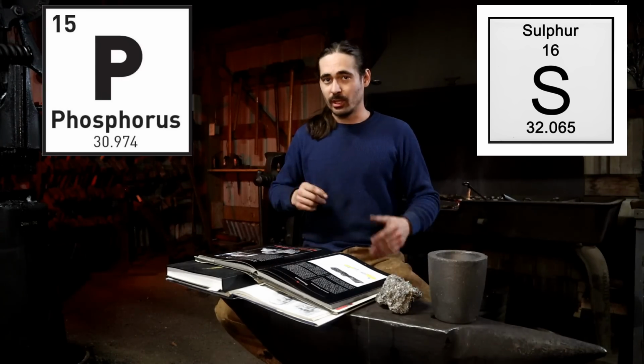What phosphorus does in your forging process is it stays outside of the grain boundary, coating it like an oil. So as you're forging it, and remember, we are working with pre-modern steels that don't have grain-reducing additives, your grain grows, but the phosphorus stays on the outside until eventually your billet or whatever you're working with starts breaking apart on you and crumbling because the grain got so large and it's all surrounded with phosphorus that the billet cannot sustain itself. It crumbles like bread. Japanese tamahagane tends to have a very low content of both sulfur and phosphorus.